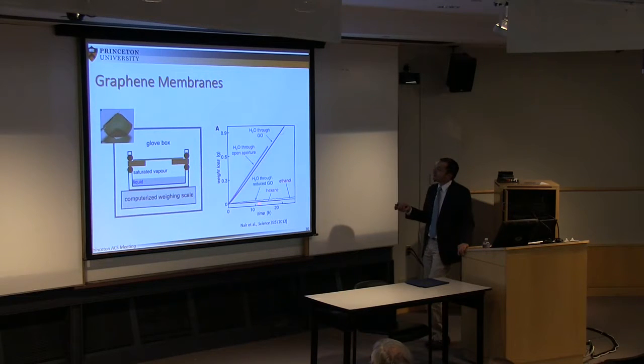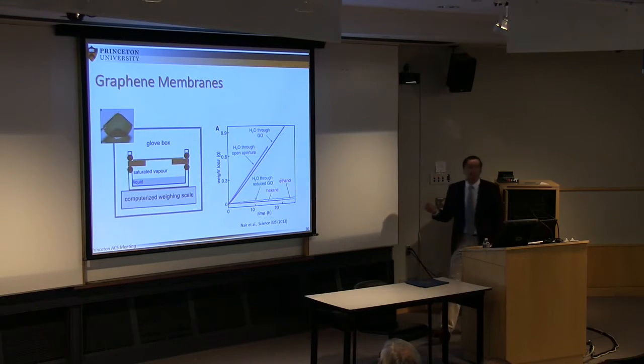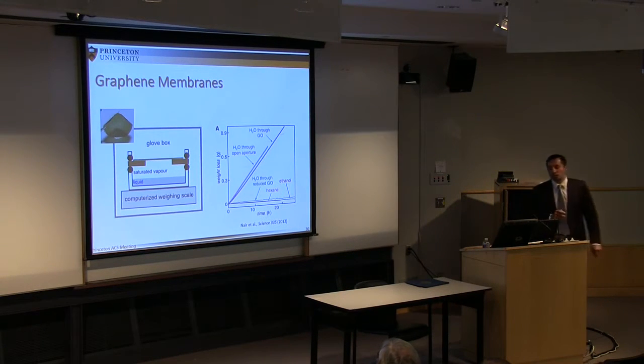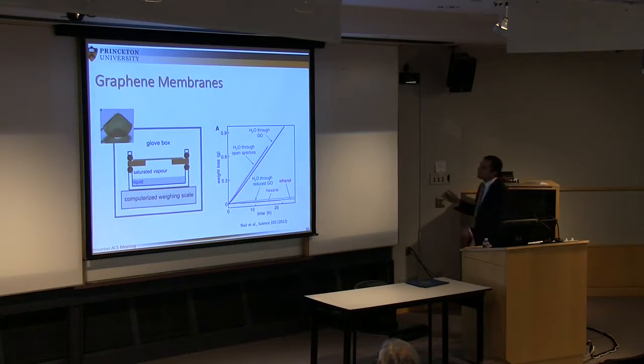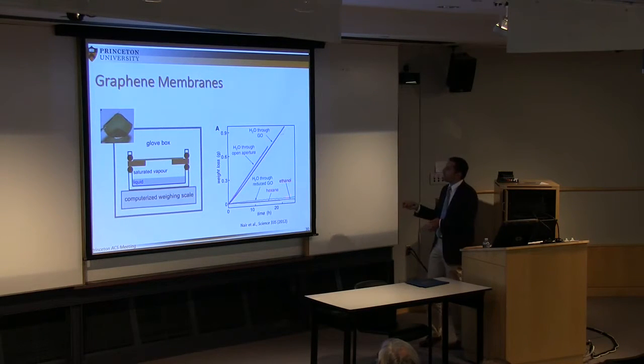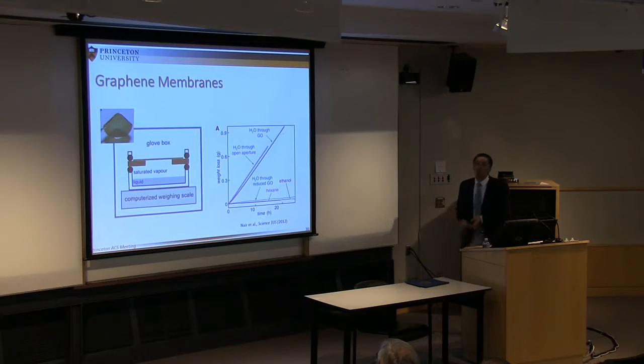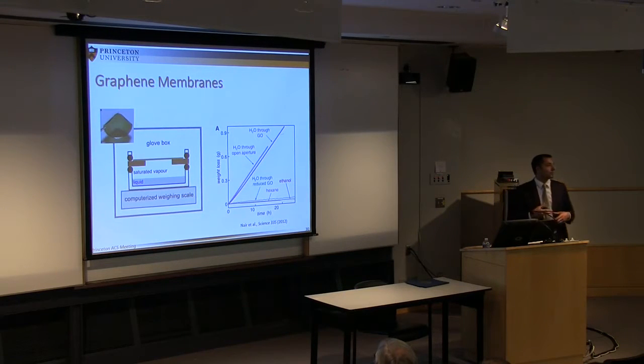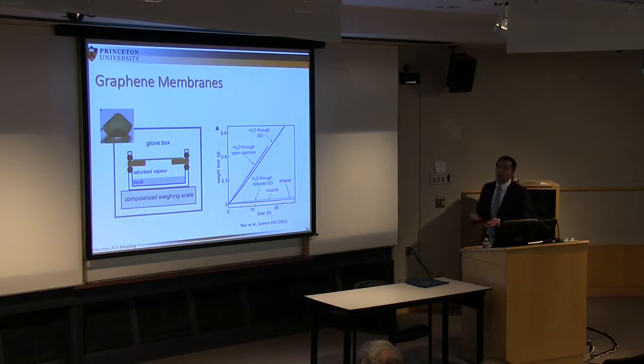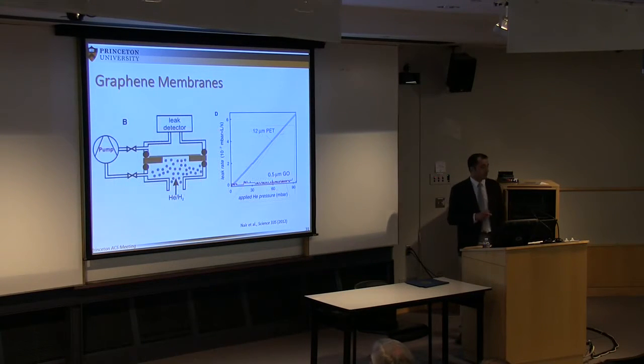So water doesn't go through, neither does hexane and ethanol, but in the case of GO, not reduced GO. So it's important here: when you reduce GO, you cannot have this. So for filtration purposes, for water treatment, etc., this can be very interesting because you won't let large solvent molecules go through, but water will go through if you tailor the properties of the graphene oxide.